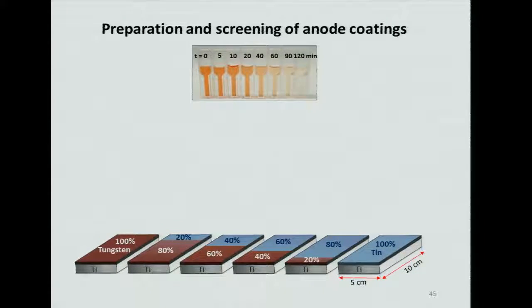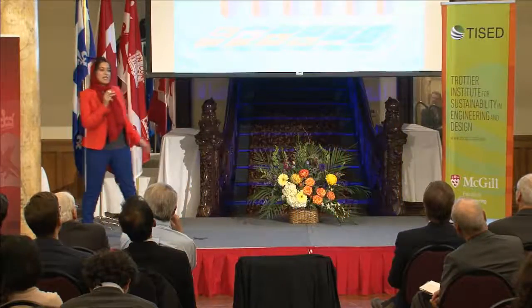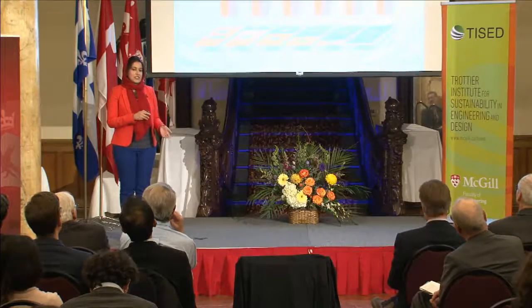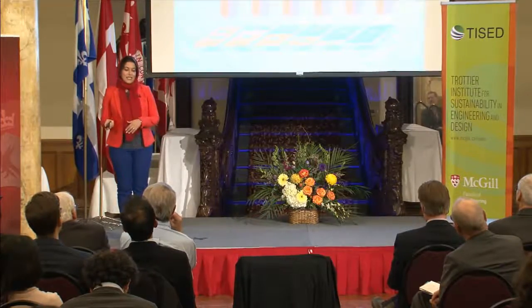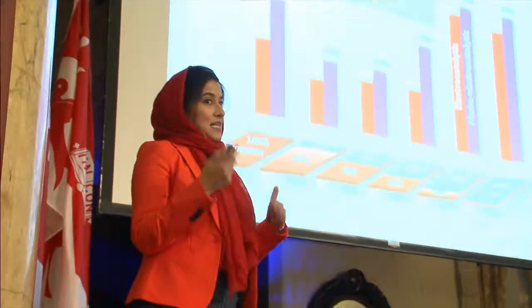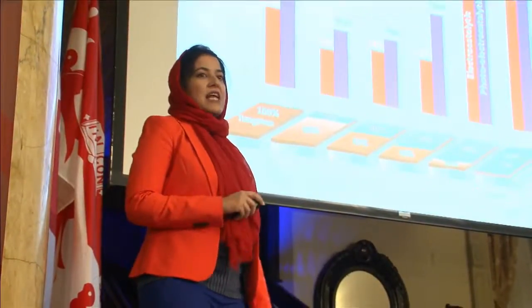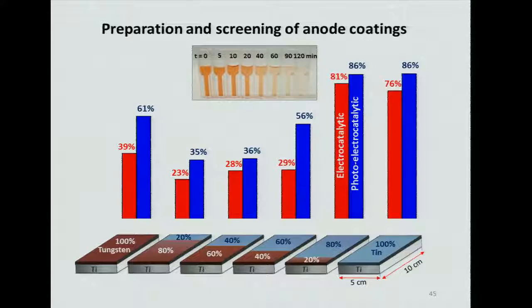The results for the removal of phenol red by using two processes, electrocatalysis, which is the use of electricity, and photoelectrocatalysis, which is the use of UV and electricity at the same time, are shown as graph bars. And as you can see, the coating composition with 80% tin oxide and 20% tungsten oxide exhibited the highest degradation percentage for removal of phenol red. So this coating composition was selected as our best candidate for further experiments.